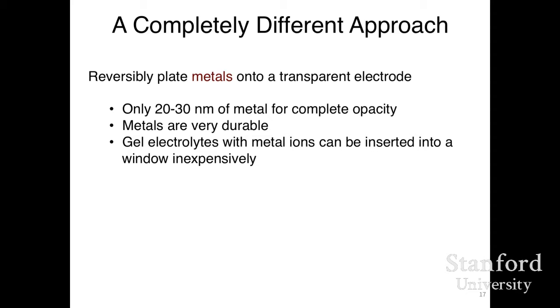And the challenge in this application is that for most of the situations, the materials are exposed to full sunlight and a wide range of temperatures. But metals can handle that without any trouble. And then in the approach I'm about to show you, we're going to have a transparent electrode, and then just a metal grid for the other electrode, and then we're just going to inject an electrolyte liquid in between, and that can be done quickly and very inexpensively compared to sputtering a couple of microns of material.